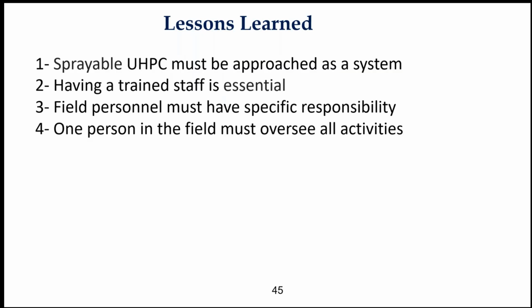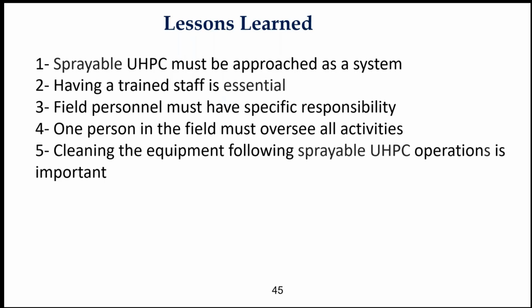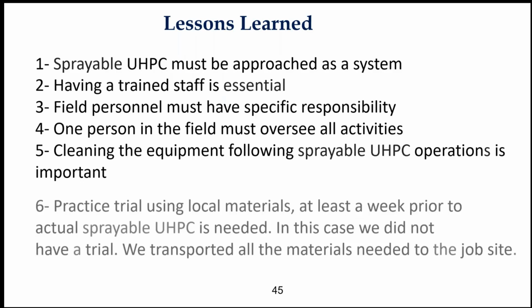If there is a problem, what you should do, and so on. Cleaning the equipment following the spray is very important. This material sets very fast. Probably, I would say the open time for this operation maybe is about half an hour, and that kind of dictates really how much material you need to fix, what is the area that you're going to fix, and so on. So this is a very important aspect, the cleaning. And if you don't clean it, it's going to ruin your operation.